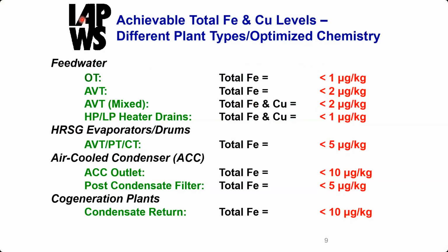This is a table taken from the IAPWS guideline that you can get freely available. And so we have developed a series of guidance for the amount of iron. And so when you have a combined cycle plant operating on AVT, say, then you want that total iron level to be less than about 2 ppb, 2 micrograms per kilogram, and that would be a good target to aim for. In the drums themselves, in the HRSG evaporator drums, on any of the treatments, we'd want that total iron to be less than 5 ppb.